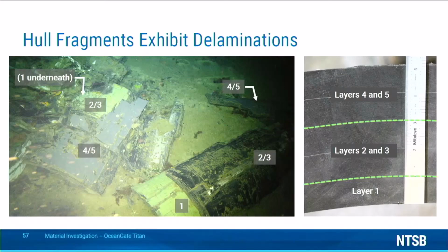Turning our attention back to the long piece from the top of the vessel at the right of the image, the separation between the middle shell and the outer shell appeared to occur primarily through the carbon fiber composite or along the interface with the adhesive. This can be seen for the piece labeled 2 and 3 on the right of the image. The dark color is consistent with fracture of the composite.